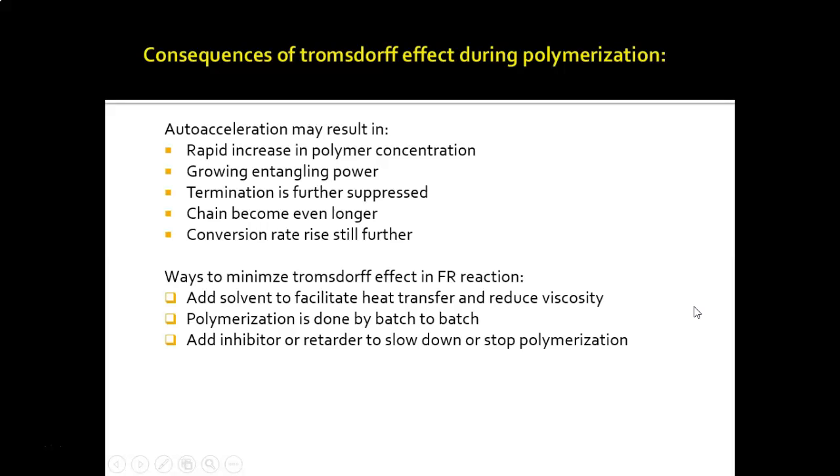Autoacceleration may result in a rapid increase in polymer concentration and also an increase in polymer viscosity. This increases the growing chains' entangling power, termination is further suppressed, chains become even longer, and the conversion rate rises still further.